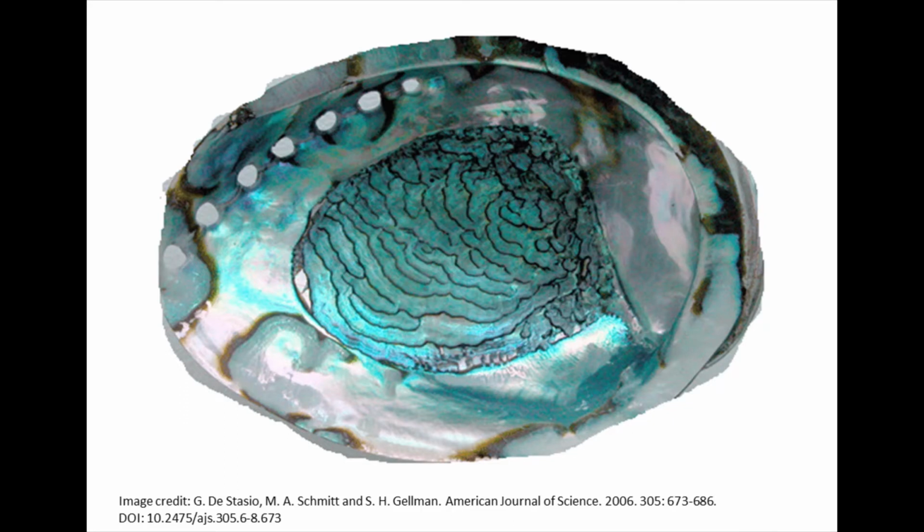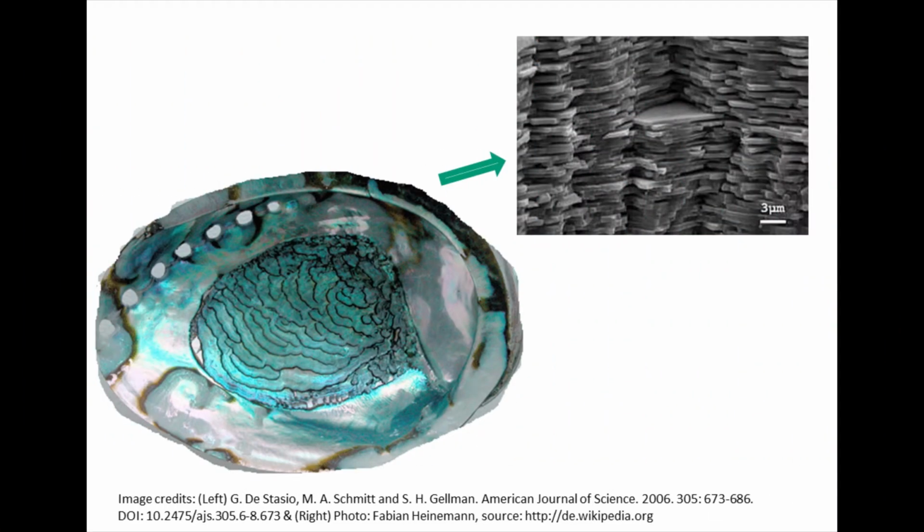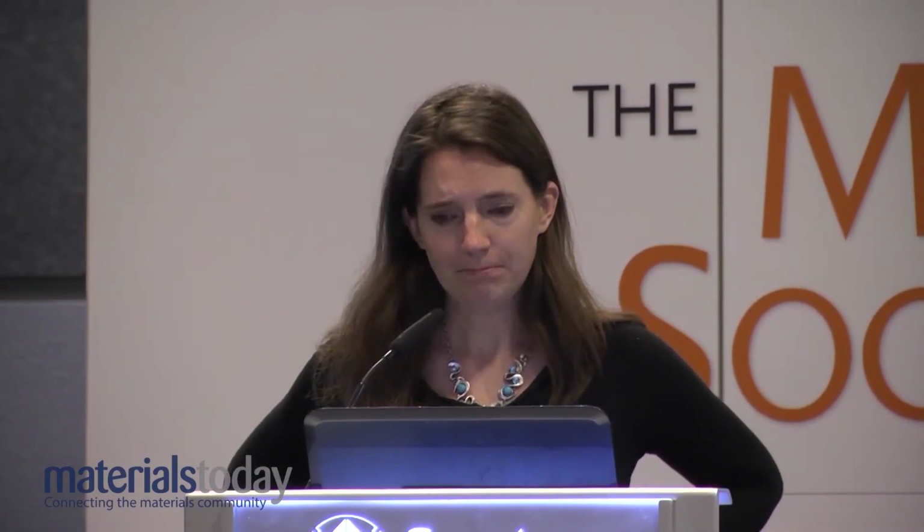And start by showing you this picture of this beautiful nacre shell. Now this used to be used by the Mayans as an artificial tooth. And it's more recently when we've been able to actually study the microstructure of this material within this field, that we can see that it actually has this beautiful microstructure composed of these platelets of inorganic material that are lodged also with some organic material. And so it turns out actually that this microstructure is very good at interfacing with bone, and so these artificial teeth, right back in the Mayan times, could integrate into normal jawbone and be used functionally.